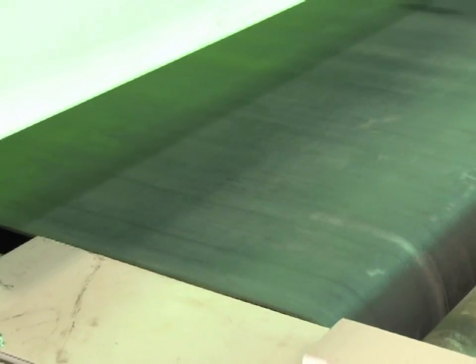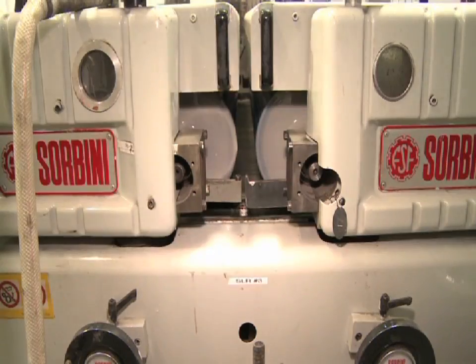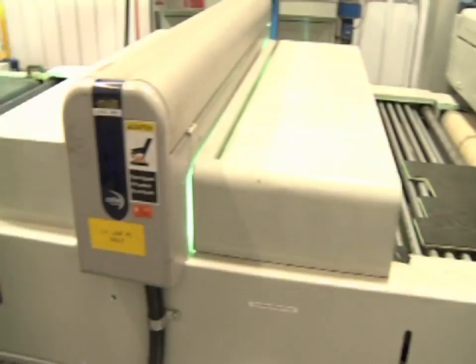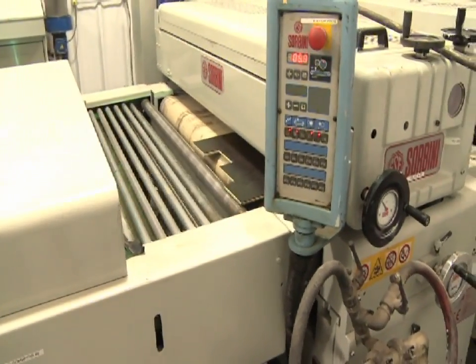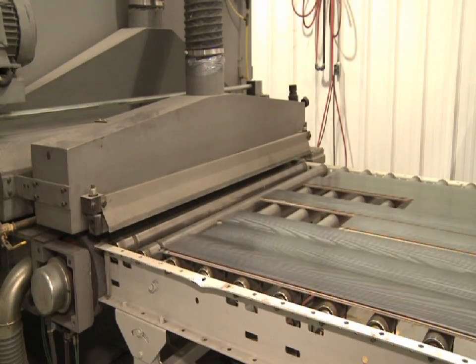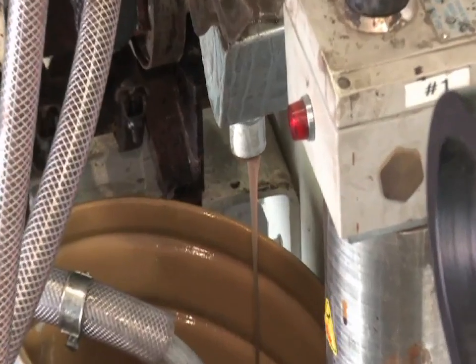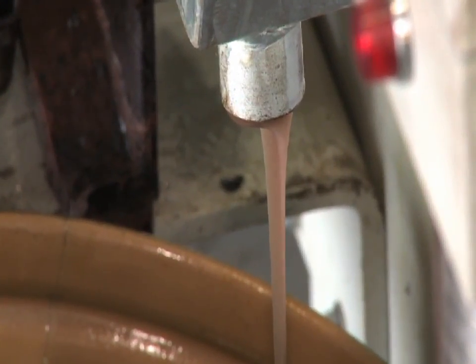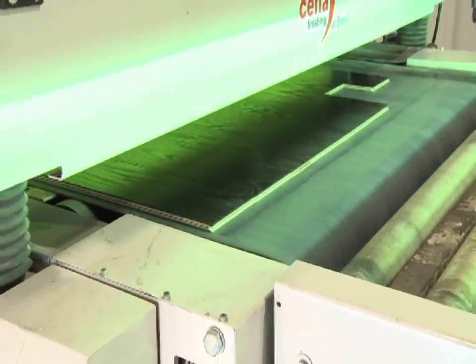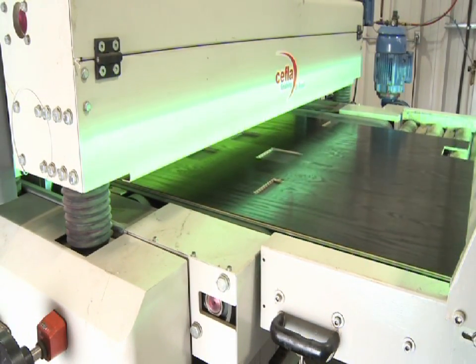In total, Vintage applies anywhere from 2 to 10 coats on all Vintage floors. The number of coats applied depends on many factors. Coating stations use rubber and steel roller coaters to allow for maximum penetration of coating into the wood. Every time a coat is applied, the panel then passes through an independent ultraviolet light box that cross-links the finish and cures it immediately.